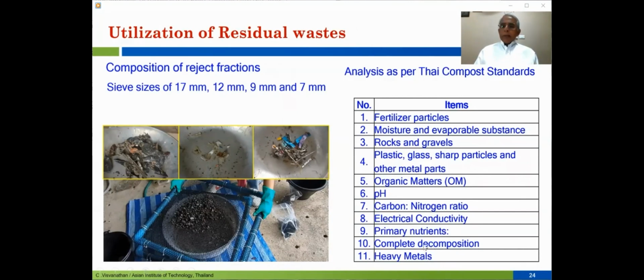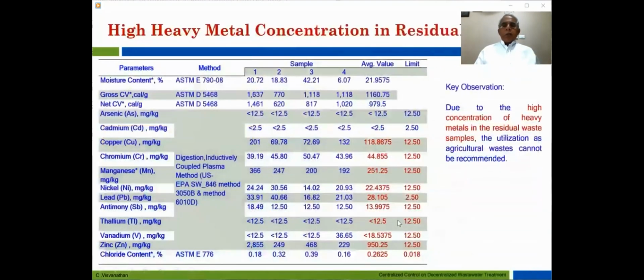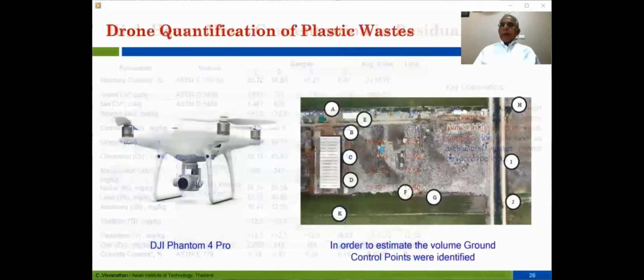We also looked at heavy metals. Is there any primary nutrients available so that it could potentially be used as compost? The detailed analysis of these samples was compared with Thailand's composting standard. It's quite interesting, the key observation: due to the high concentration of heavy metals in the residue, and looking at the other parameters, direct utilization of this residue as compost is not possible. So we need to look at some alternative, and that is one of the issues when we wanted to look at plastic recovery from the dump site and what you do.